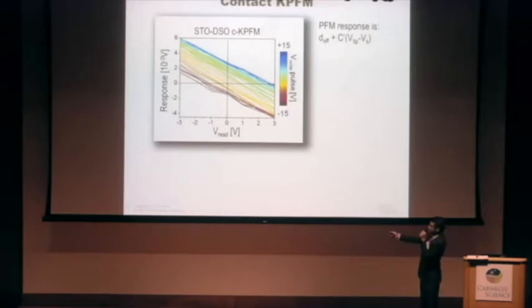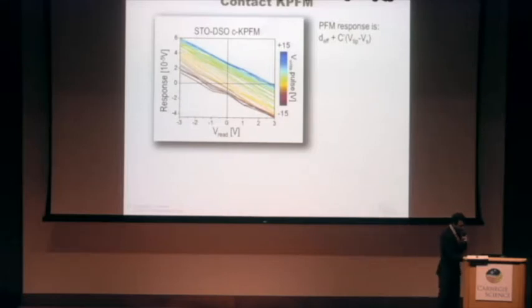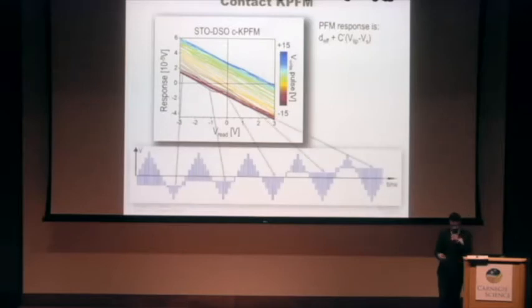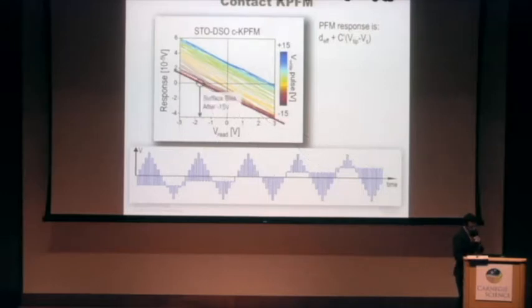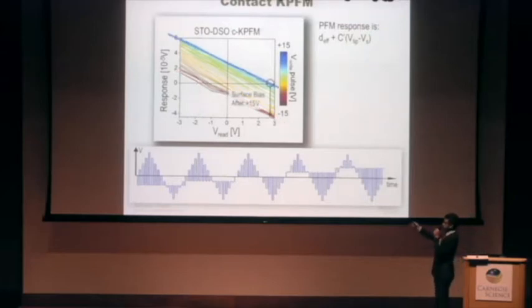The x-axis at the bottom is the read voltage, those offsets that I showed you before. Each one of these points comes from these offsets at a particular write voltage, which is given by the color. So if you go along this line, it tells you the surface potential after applying some voltage. In this case, after we apply minus 15 volts, this red line here, you can read the surface bias, which is around minus 2.7 volts. Similarly, you can do that on the positive side. After applying plus 15 volts, you see that the surface bias is something like 2.8 volts.